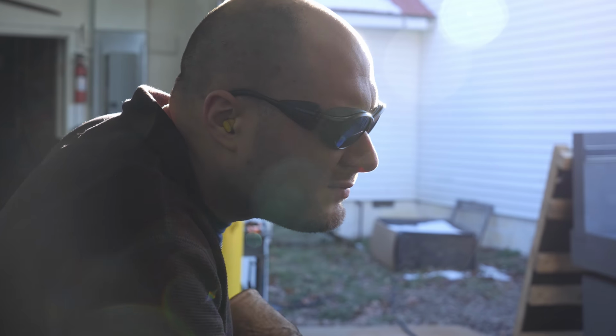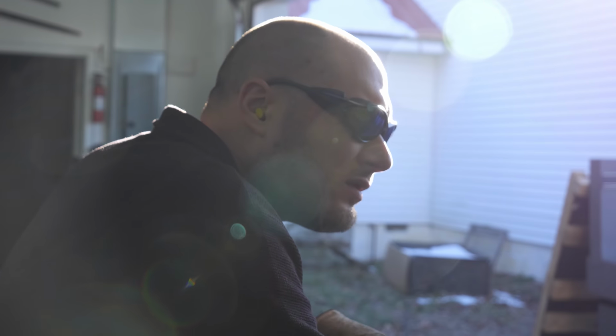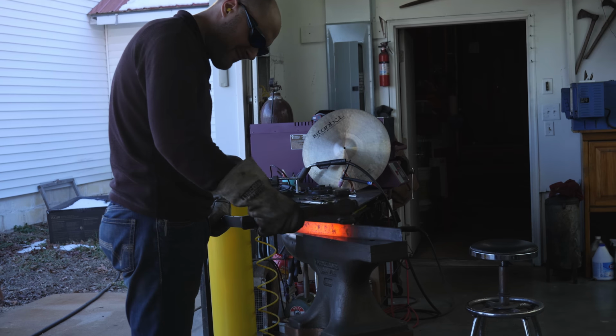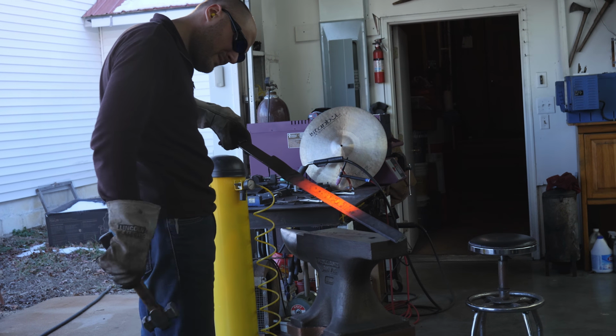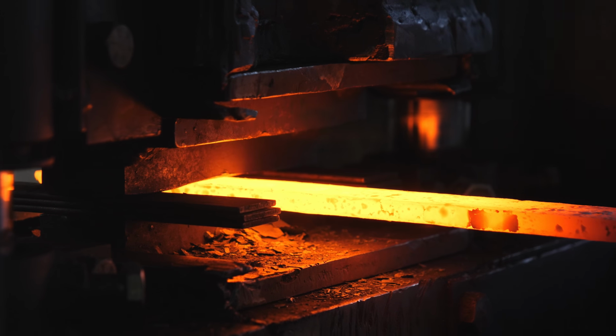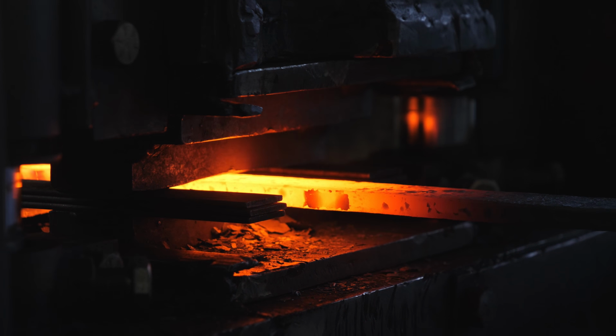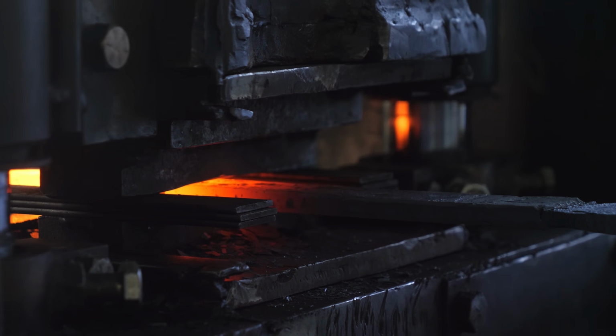Whew, I think I caught it just in time. I don't see any cracking on the billet. I think we're good. I let the billet cool down just enough before forging it out, and thankfully it didn't crack or start falling apart in the forge.